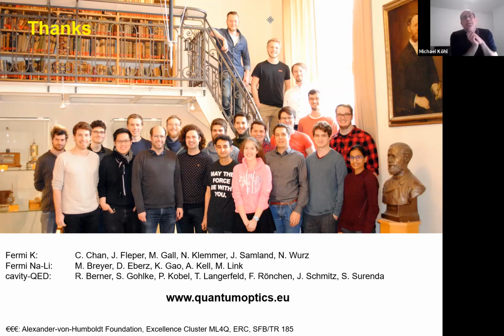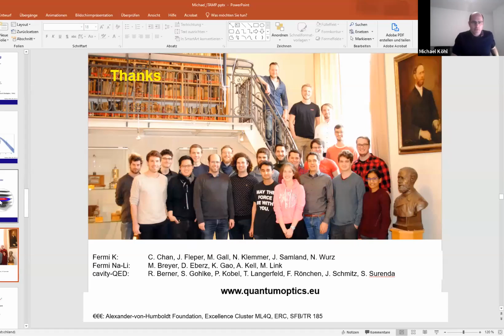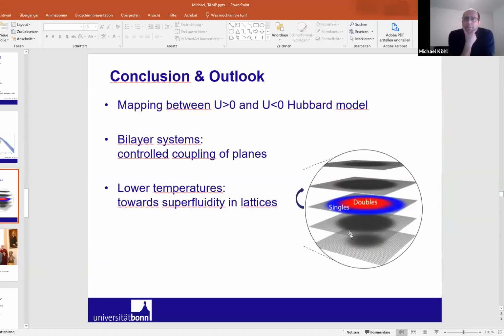We apply a magnetic field gradient in the Z direction in order to slice out the individual layers for detection. Let me go back to my intro or this transparency. What we do is we create a three-dimensional cloud of atoms. We load this into this stack of planes. And the physics is happening in all planes simultaneously. But for detection, we select one of these planes by magnetic resonance. So we apply a vertical gradient, slice out one plane, and then do the detection only on this plane.